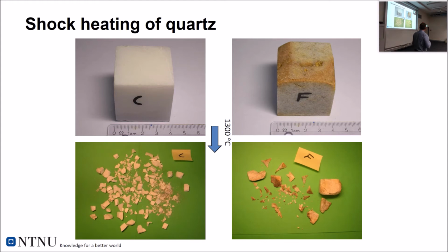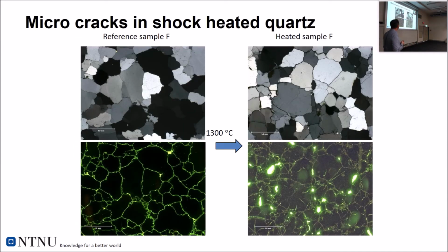So we looked into these products from the shock heating even further. So we moved to the microscope, made thin sections, and impregnated the material with fluorescent epoxy resin that we could use in the UV lab to see fluorescence, to study how microcracks in the material have developed.